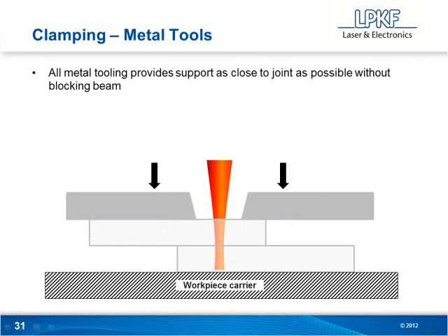Another option is to use metal tooling, so we're just supporting or clamping the joint from either side as close as we can get to it. Tony mentioned an issue sometimes what you'll see, and again, this is entirely dependent on the type of plastic. Because of the volumetric heating, you might get a small swell on this upper layer if you're not applying clamp force there. That being said, it's completely material dependent. We've seen results both ways. Sometimes you don't see it at all, and sometimes you do. So again, it just goes back to us testing the parts for you.